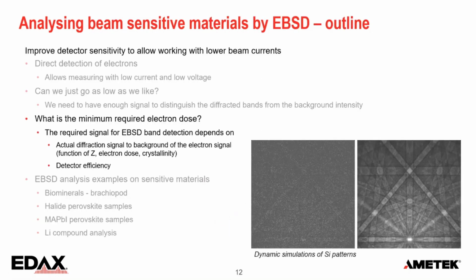Now, what is this minimum dose? Because I just showed some examples on nice diffracting materials like steel, iron, that give very strong patterns anyway, but the signal levels that we get also depend very much on the backscatter coefficient. So the atomic number, it depends on the electron dose, it depends on the sample very much. How crystalline is it? How clean is the sample surface? And also a little bit on the detector efficiency.